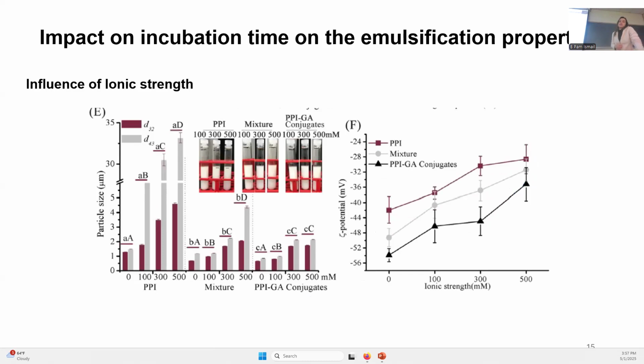And then they looked at the ionic strength. So they made the emulsions again and added different concentrations of salt, 100, 300, and 500 millimolar, and looked at the particle size and charge again. We can see that for PPI, after they added 100 millimolar, we saw a dramatic increase in the particle size, and that we didn't see for the mixture and the PPI and gum arabic conjugates. Other than that, there's very little difference between the mixture and the conjugates for the particle size. But we also saw a difference in the charge. They have the same pattern, but the conjugates have a more negative charge compared to the other ones.